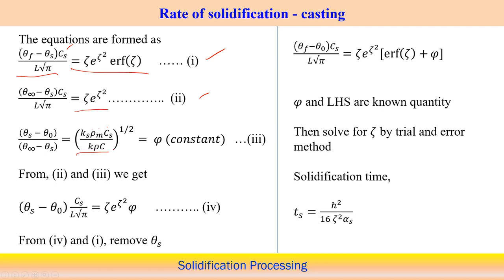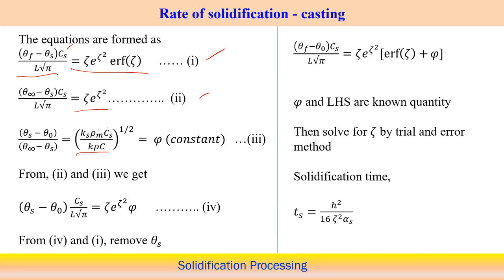Actually, k, rho and c are the properties of the mold material, and k s, rho m and C s are the properties of the cast material. The square root of that equals phi, which we can see as a constant. Here we have to be careful about which properties we are utilizing: both the mold material properties as well as the cast material properties. For this particular combination of cast and mold material, this becomes the constant term.